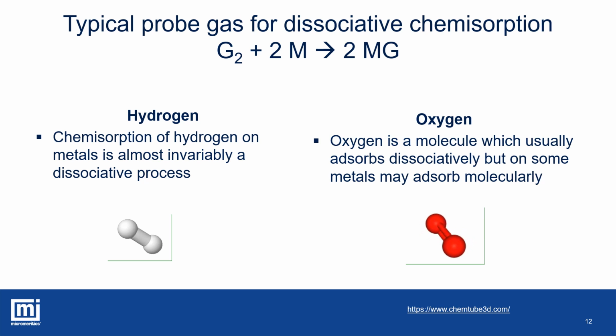Oxygen can be used with metals showing easy oxidation properties. The disadvantage of using this gas is that oxygen might change the surface active structure by corrosive chemisorption. In dissociative adsorption, oxygen atoms are strongly bound to the surface and will tend to occupy the highest available coordination site. The strength of the interaction between adsorbate and substrate often causes the displacement of side metal atoms.